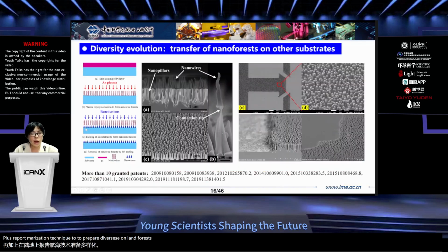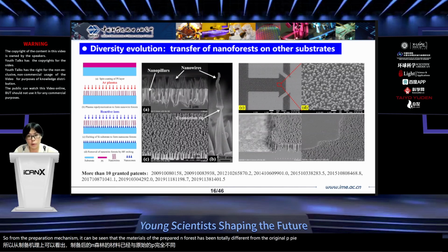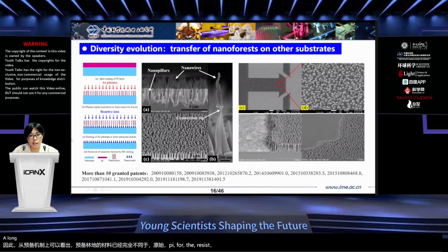Based on the above deduction, we propose a silane coupling agent-assisted plasma repolymerization technique to prepare diverse nanoforests. So, from the preparation mechanism, it can be seen that the material of the prepared nanoforest is totally different from the original PI photoresist. After a lot of tests, we now know that the nanoforests are made of elements of silicon and oxygen, which is similar to silicon dioxide. Therefore, it can be further used as nanomasks for silicon substrate etching to transfer the nanoforest to the silicon substrate.